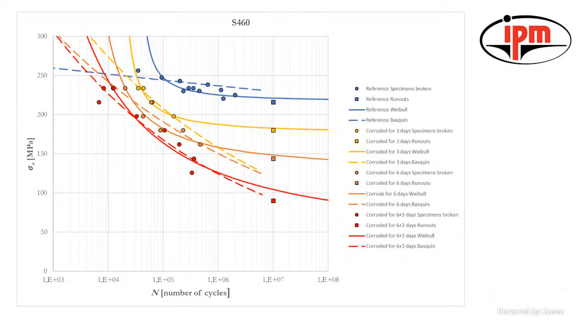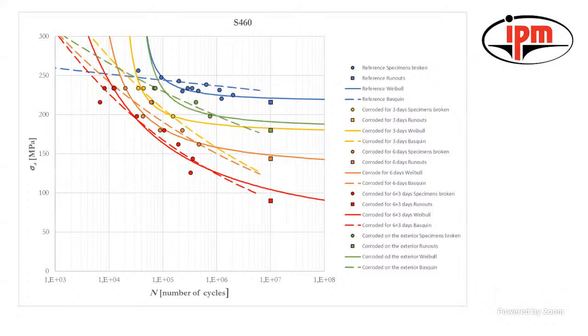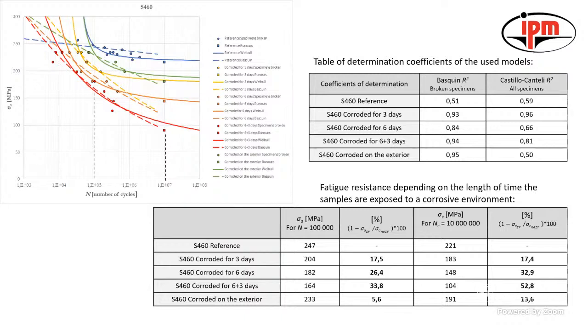Okay, you can see 3 days, then, as we supposed, 6 days and 6+3 days. Then we added the corrosion effect after 1 year on the roof. You can see that this is between the clear and up to 3 days. It means that if we wanted to simulate the situation in the Czech Republic, what happened with the high strength steel, the corrosion effect, it is clear that we could use 3 days as approximately 1 year of corrosion, or less than 3 days. Okay, there is some clear evaluation.